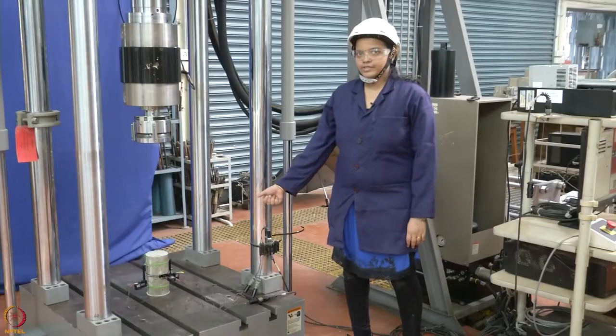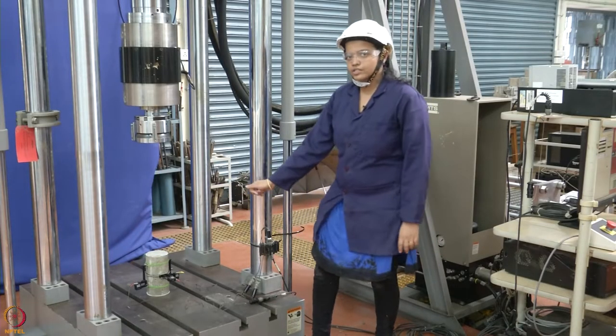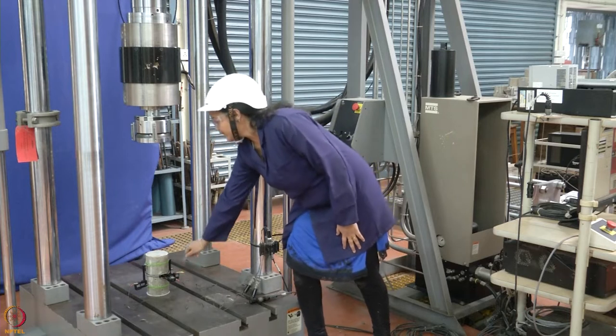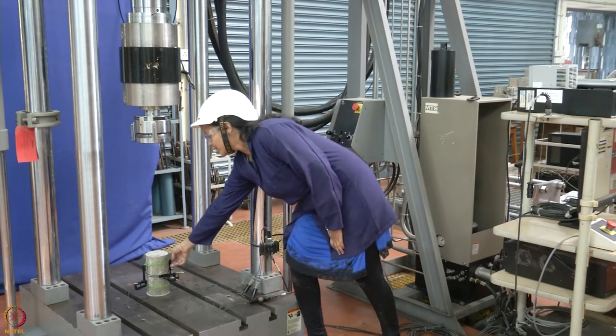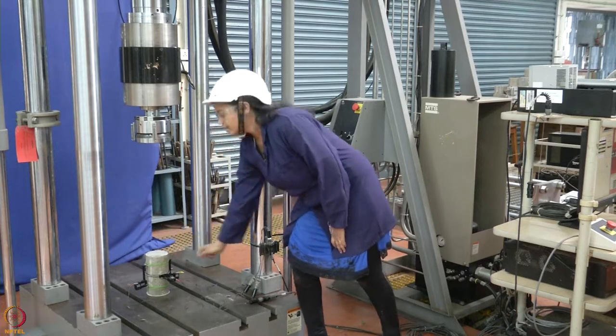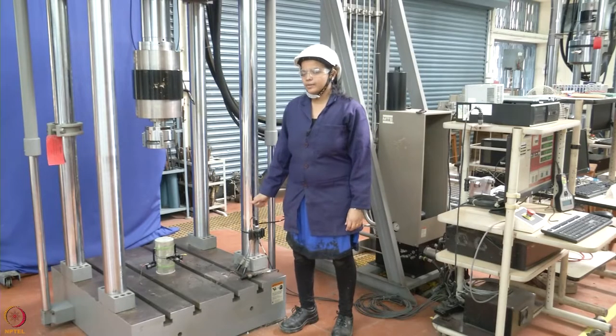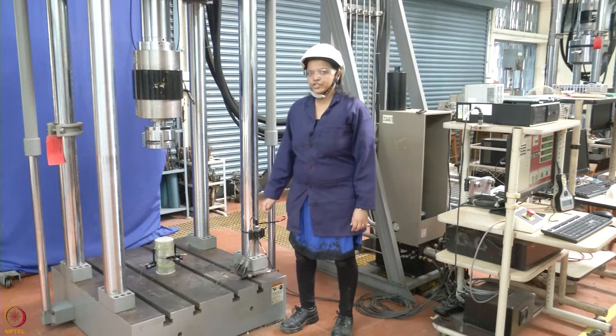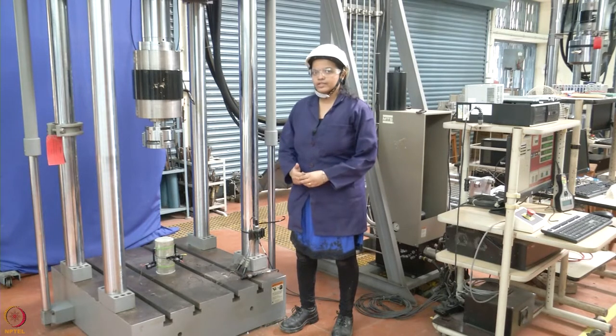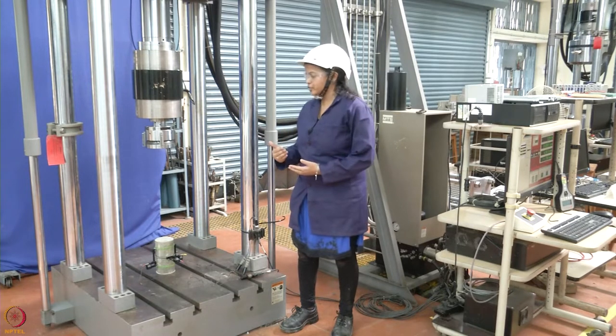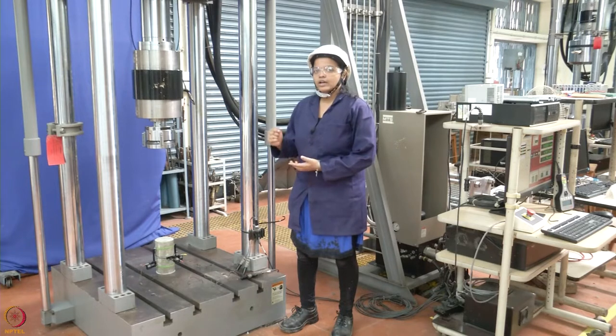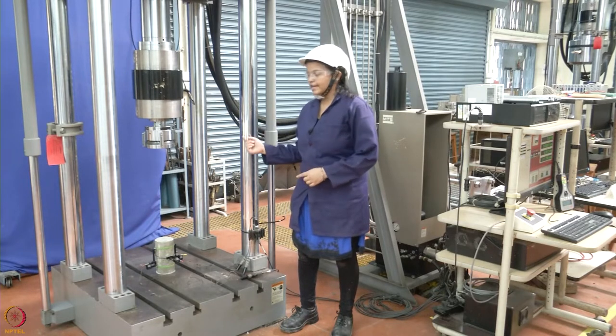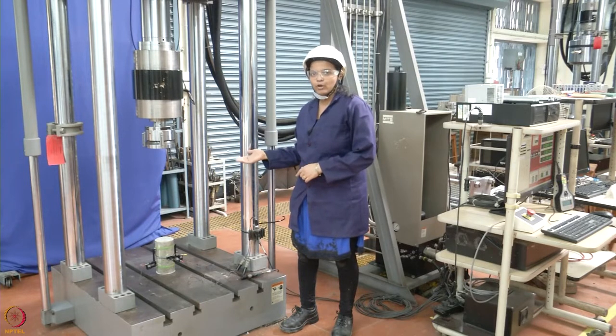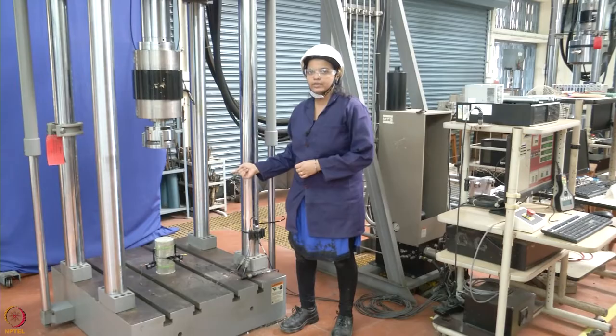Now the testing setup is ready. The circumferential strain is going to be measured by this extensometer, and the axial deformation is going to be measured by these two extensometers. In this test, we will control the testing by means of the circumferential control. This is done because the circumference is always going to expand, whereas the axial deformation will always compress. But what happens is, if a crack occurs near the extensometer, it might slip off. That's why we are using this circumferential control in this testing.